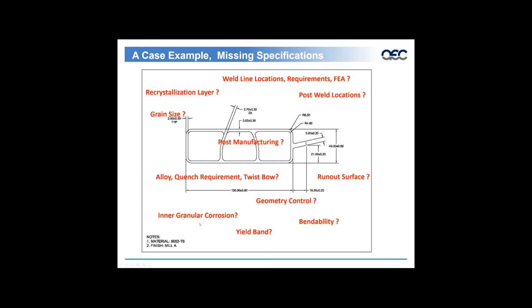And once that's understood, then we need to start to understand what are the tolerance requirements. And based on that alloy and based on that quench rate, do we need to apply tighter controls relative to the dimensions and also take into consideration twist and bow? As we talked earlier, based on those alloys and based on that mag silicon content, it's going to determine the quench rate required, which will ultimately have a better understanding of what the twist and bow is.